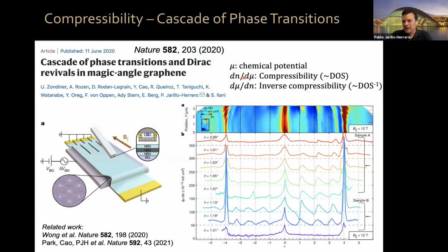And in the simplest case, in single particle physics, the compressibility is just proportional to the density of states. The inverse compressibility, or how does your chemical potential change as you add charge to your system, that's known as the inverse compressibility. And again, in single particle physics, in the absence of interactions, that's just 1 over the density of states. So in this paper, we reported measurements of the inverse compressibility, d mu dn, as a function of filling factor for magic angle graphene.